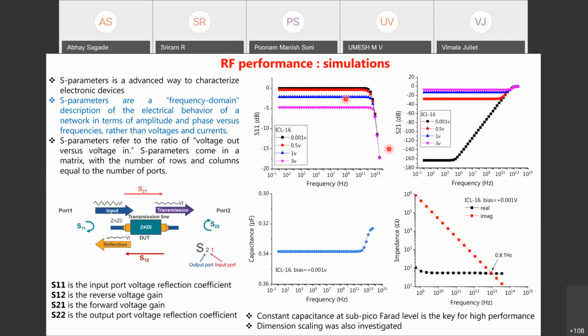Then you can see it is a completely flat line up to terahertz frequency. And the second, if you look at S21, you can see the variation is approximately linear up to that same frequency range. From these S parameters, you can obtain the capacitance of the device, and it has to be very, very low. If you want larger cutoff frequencies, then this capacitance has to be very low.